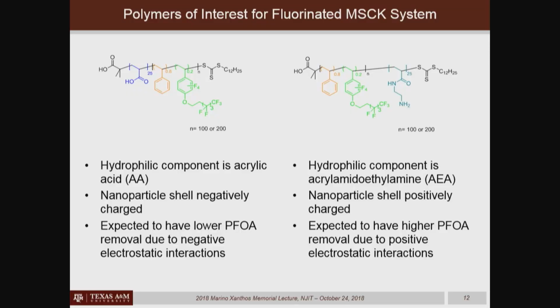So again, coming back to the chemistry, Adriana had said, well, the polyacrylic acid block polystyrene material works so well with the crude oil cleanup. Let's just throw a little fluorocarbon tail on a fraction of the styrenyl repeat units along that hydrophobic block segment of that, what was a diblock polymer structure. And then again, replacing this carboxylic acid group with an amino group, she looked at an aminoethyl acrylamide as the hydrophilic block segment and replacing the polyacrylic acid to see how the influence of the chemistry of the shell would play in the ultimate performance of the materials.